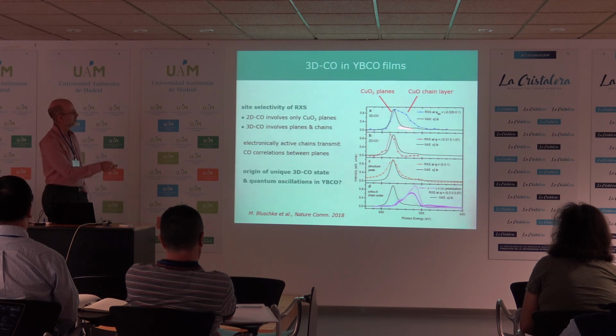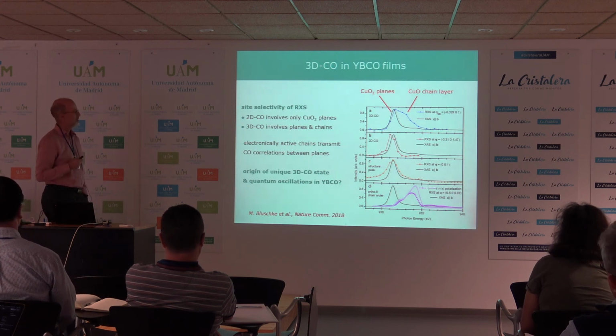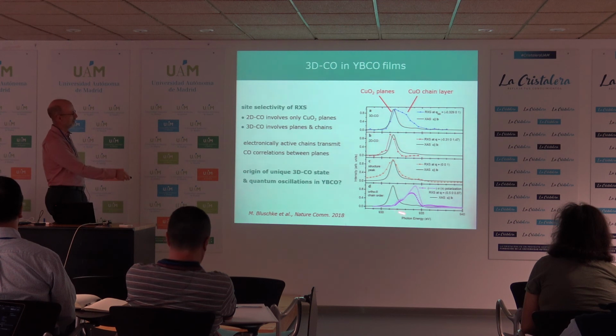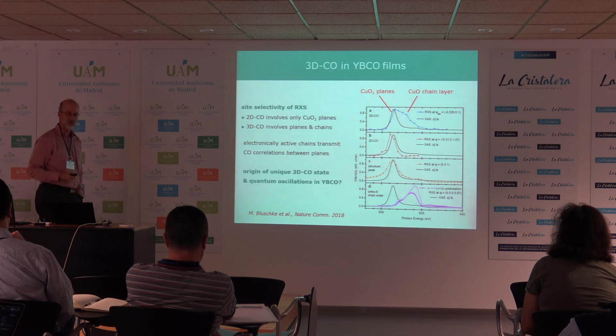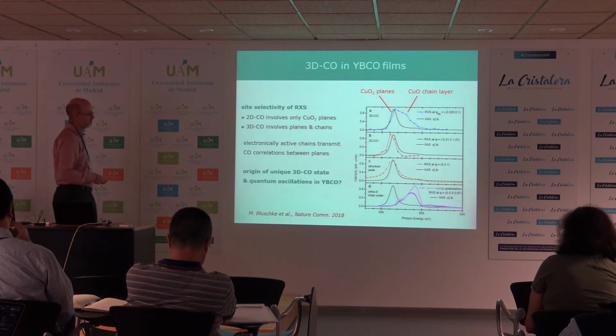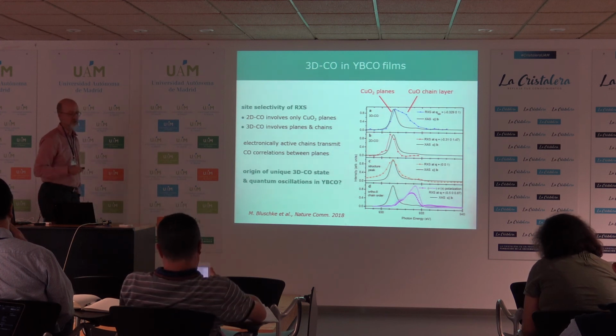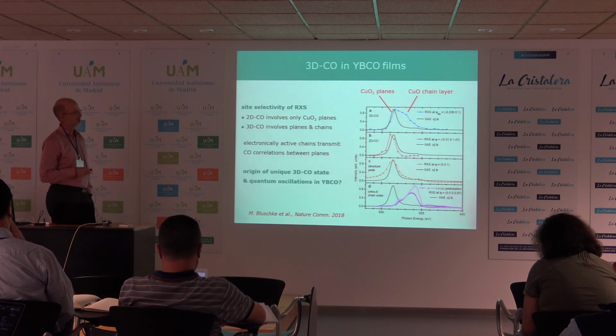So for the 2D charge order, I told you that it resonates at the energy characteristic of in-plane coppers, right? Then you have here a peak that's characteristic of oxygen order in these materials, and the oxygen order is happening in the chains, right? So this ortho-2 chain order resonates at the energy that's characteristic of the copper-oxide chain atoms, right? So these are two different resonance energies.